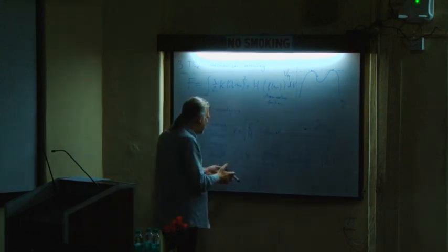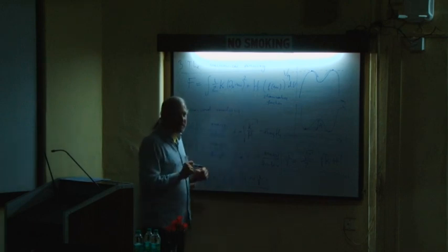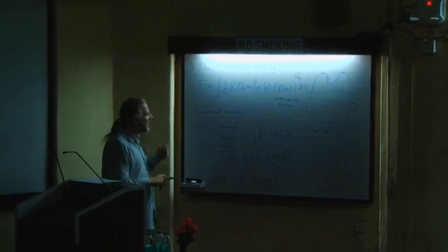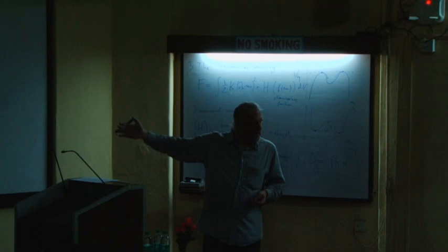So you contribute this energy penalty over a width epsilon, and that's why the surface tension has to be proportional to the product of the thickness times the barrier height. Okay? So all of this is very intuitive, and it explains why this free energy functional naturally contains domain walls with a domain wall energy and a natural domain wall thickness, which is the main strong point of phase field models.